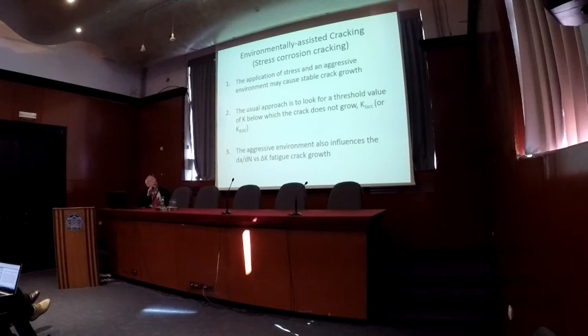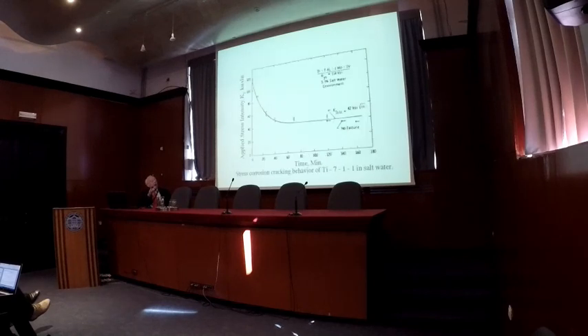Now, here's another behavior. The third one that I mentioned is environmentally assisted cracking, and that entails the application of a stress and an aggressive environment on a cracked body. And usually the approach to that is to have then applied K versus time to failure and try to find a region where you get no failure and call that a threshold. In the old days, it was called K1SCC, K1 for stress corrosion cracking. Now the new terminology is K1EAC, environmentally assisted cracking. Anyway, this is kind of how that looks.